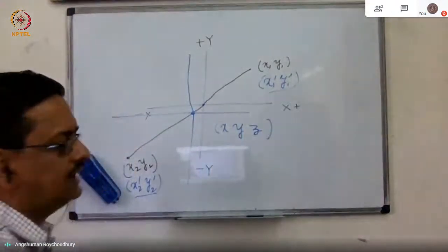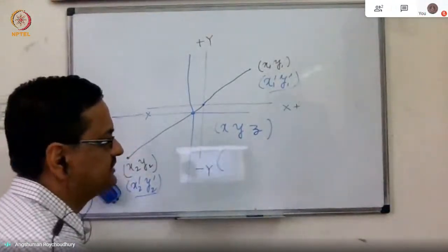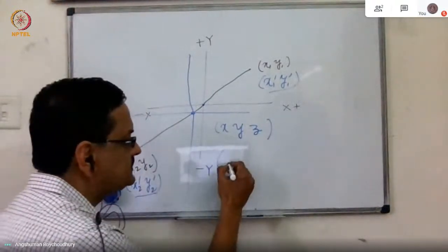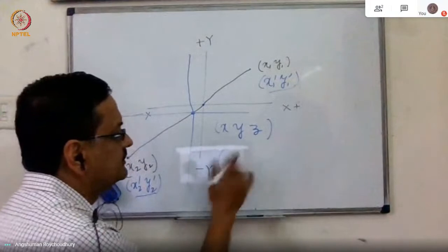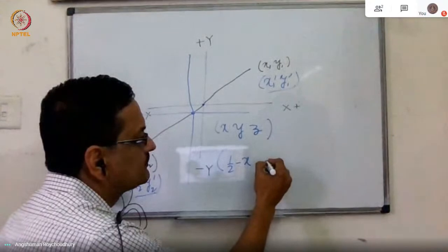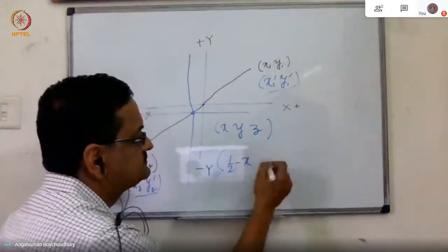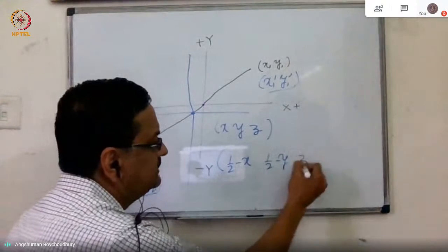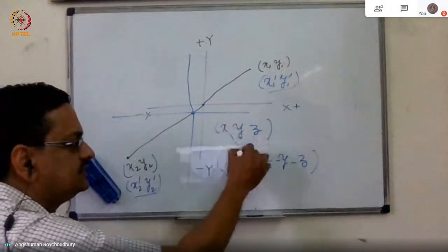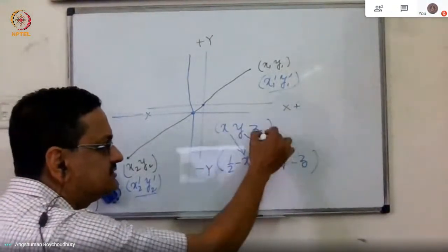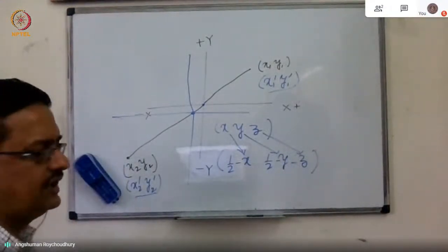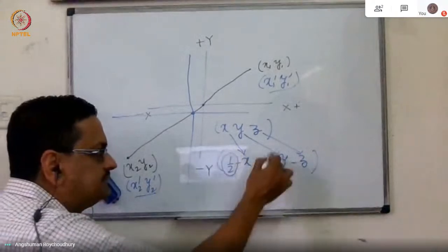and you will see that there is a point which is, in case of P21/c, I think it is half minus x, half minus y and, sorry, minus z. So here you see the relationship is inverse. The relationship is like an inversion center. x is going to x bar, y bar, z bar, but there is a component half which is associated with